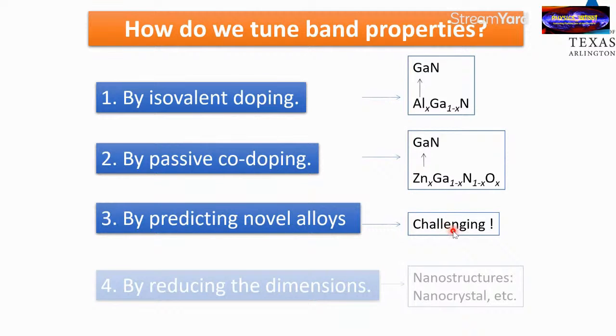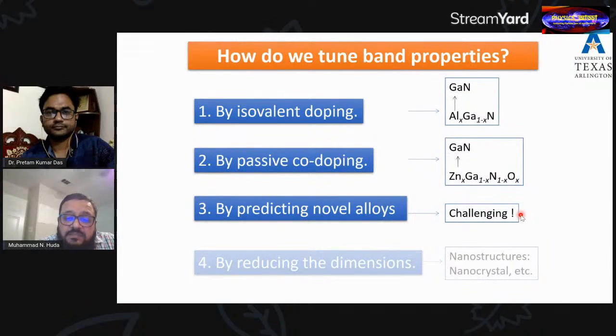This is challenging. This is not very easy because, as I mentioned, in DFT the information it needs is the types of atoms, elements, and the crystal structure, where the atoms sit, those positions. If I have a completely new alloy, I don't know the crystal structure in that case. Hence, the first challenge was to predict the crystal structure. Predicting crystal structure from first principles is still one of the most challenging tasks to do.